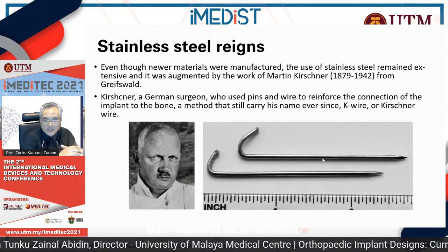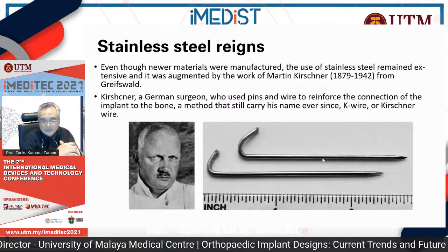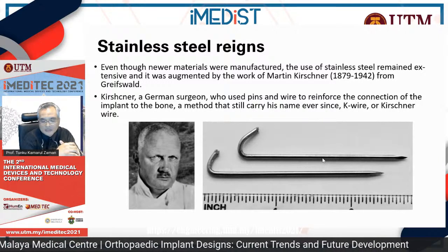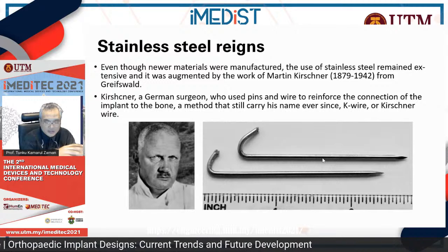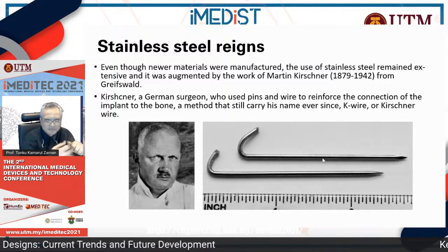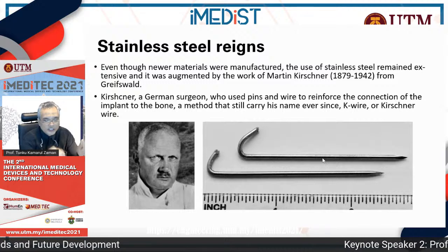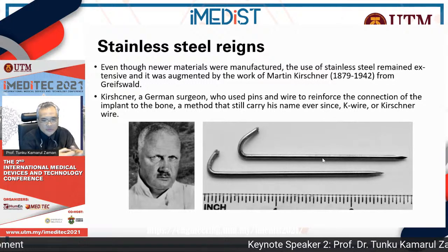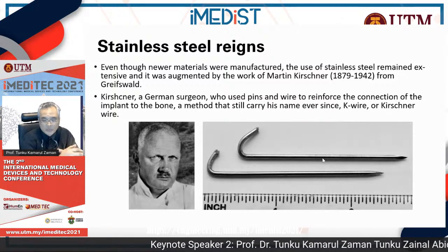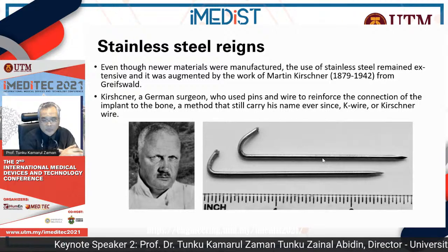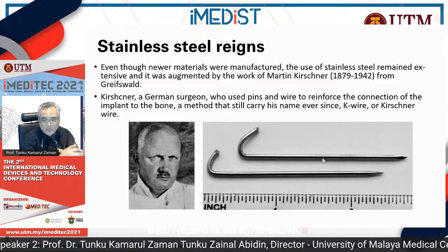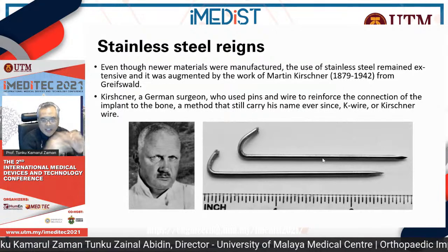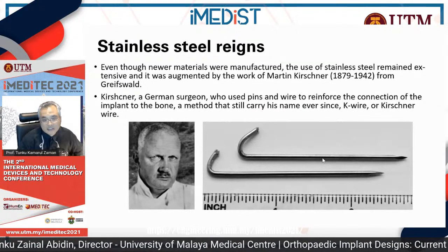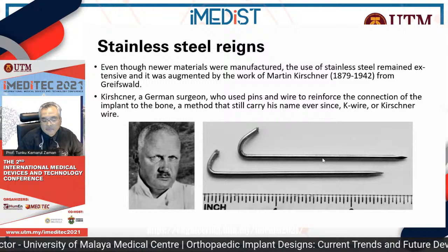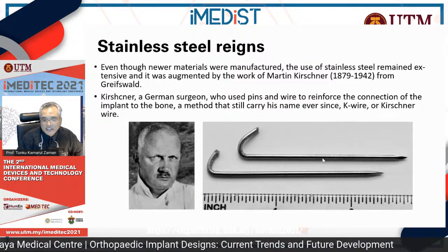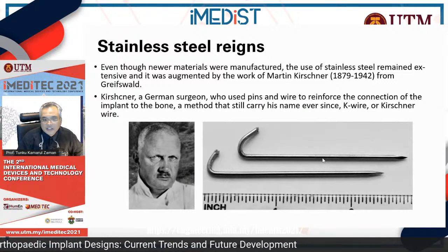And one of the things that the British became envious of was that at that time all their pilots, when they were shot down, were kept in hospitals on a stretcher, and they had traction to just hold the bones, and it took them something like 3 months to heal, whereas with wires holding the fracture very quickly, these guys were up and about in less than 4 to 6 weeks, and they were flying again. So they had a faster chance of training pilots in Germany. So he developed this material and the technique that is used even today. I still use what we call the K wire.